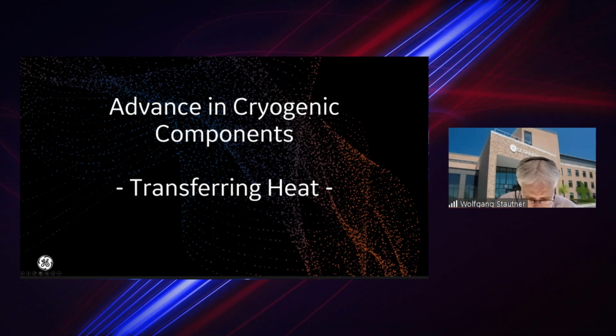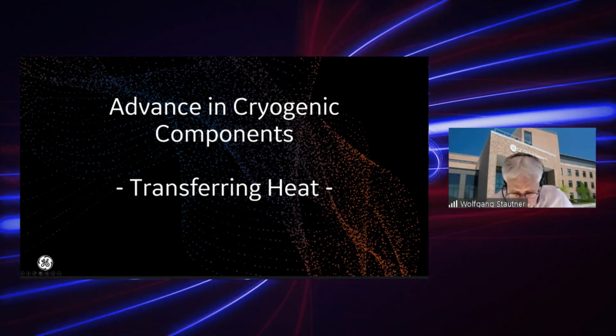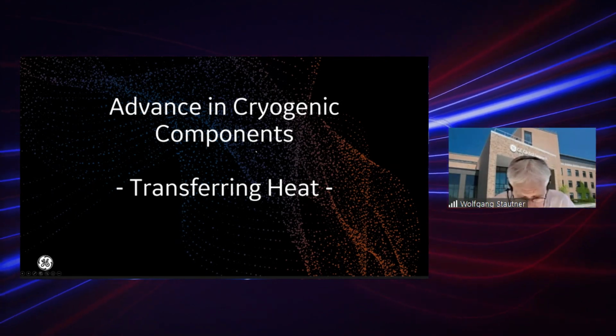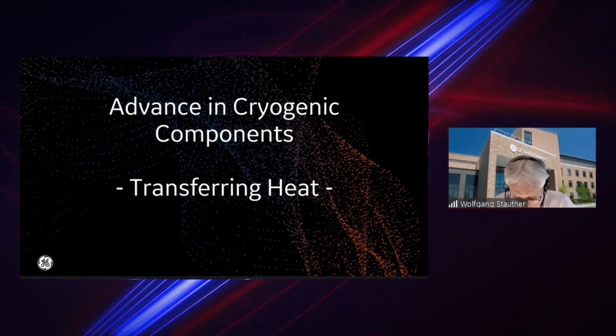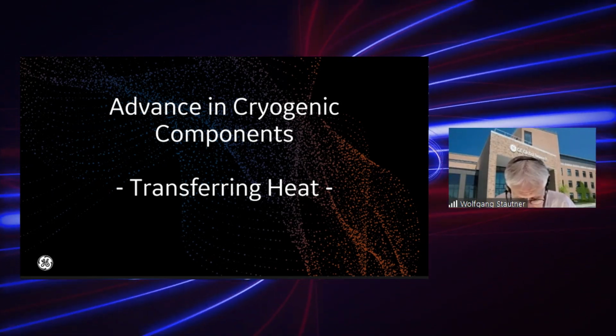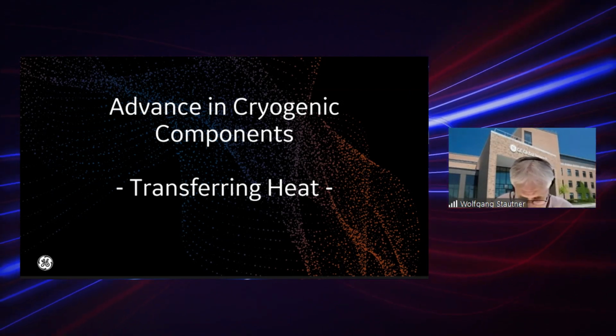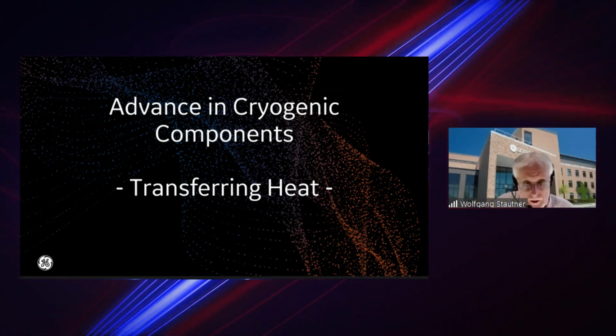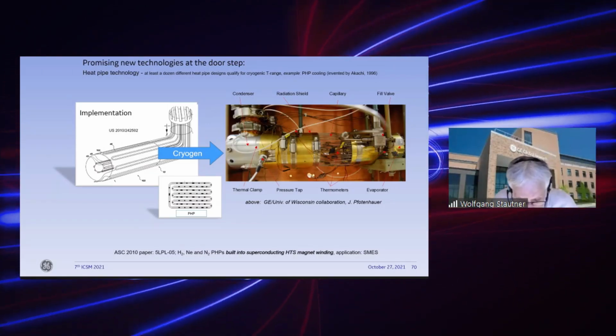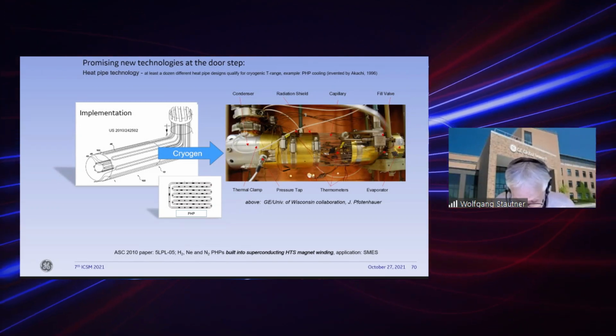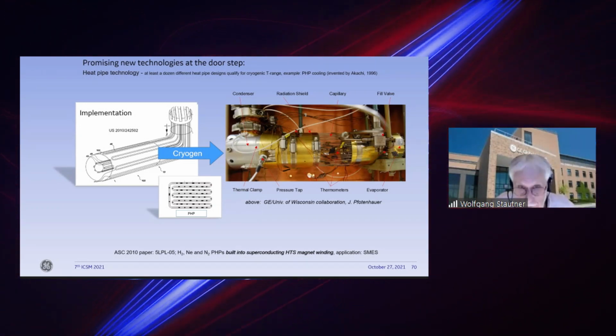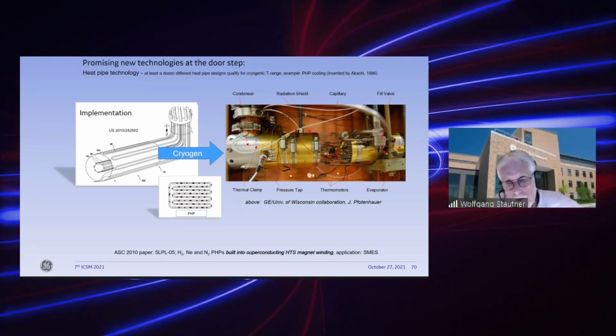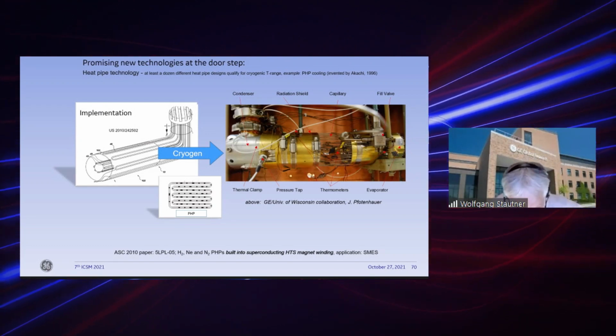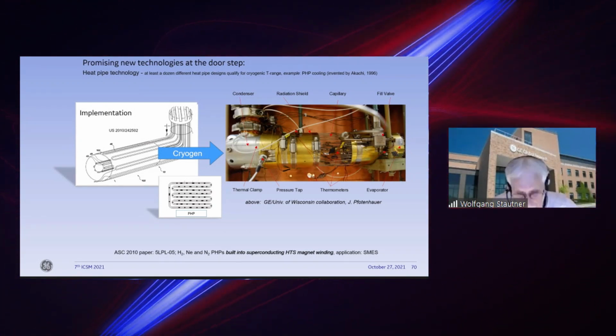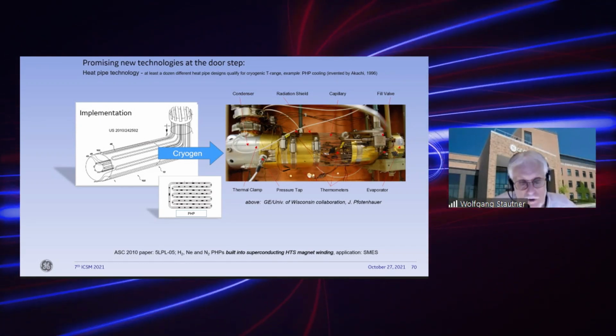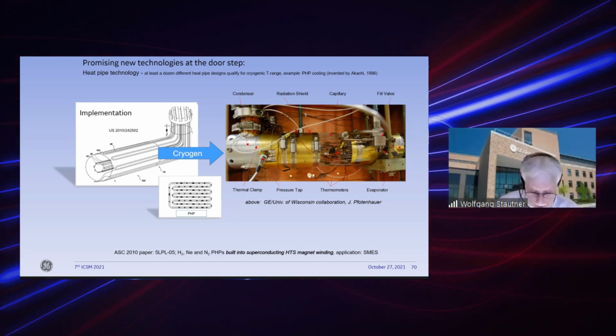We now shift gear again a bit to how we actually transfer heat from a warm end to a cold end in a cryosystem, and that's quite interesting because that's what we need to do all the time. We have to have kind of cold plates or heat buses, and this slide shows a very advanced way of achieving this kind of heat transfer, and that is by using pulsating heat pipes. This is a technology that GE sponsored and initiated actually, and postulating it as an advanced way of transferring heat in large cryogenic structures.